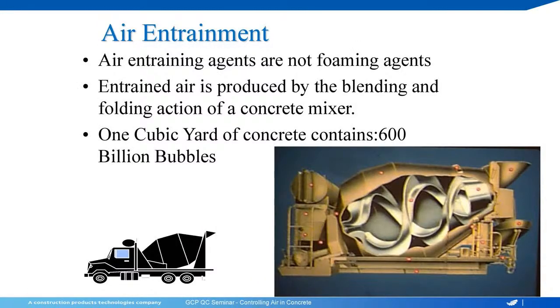So one thing about air entrainment, it's not a foaming agent. If you put air entrainment into your concrete, you're not getting air until you mix that concrete. We're going to talk a little bit about mixers and how they impact the air. But if we don't mix it, we're not getting it. Just like when you wash the dishes at home, you put the Joy into the sink with water, and until you get some agitation, until you stir the water, you don't get the foam. It's the same with air entrainment. You have to have mixing.